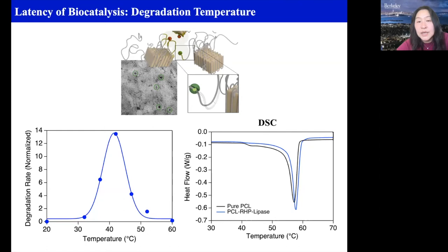So this really helps us to guide and provide several approaches. One is we're basically using polymer chain mobility, looking at polymer diffusion. And that really follows the DSC. DSC tells us when the polymer chain starts to melt. And we got pretty lucky, which helped us open up a window where the degradation rate becomes really high around 40 to 50 degrees. That happens to be the temperature in the industrial composting facility. And what is also important is that as the polymers start to melt, you have very little entropy driving force, and even though the polymer chain has mobility, it really doesn't degrade. This is really good news. It was not by design, because you don't want a polymer to degrade during melt processing in the extruder.